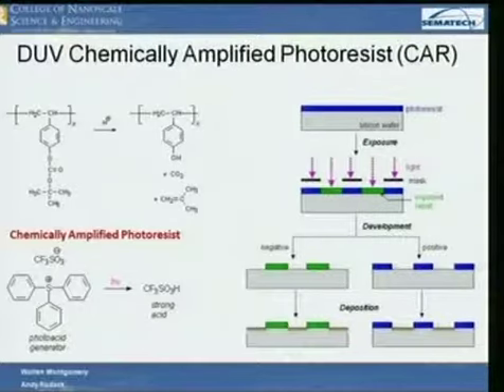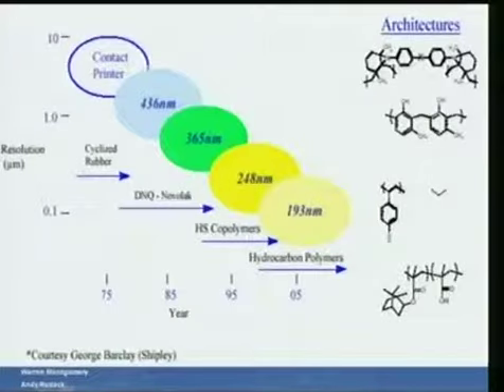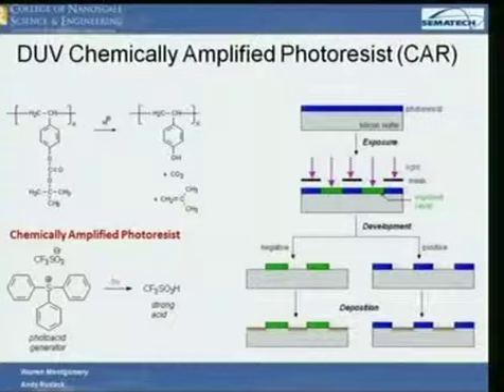And the other thing about that is that CO2 helps us, because if you expose something and you generate a gas, the gas comes off, what do you get? You get holes. So if you get holes in the area where you're exposed, what happens is the developer is able to penetrate the film better. So this thing had accelerated development because both of these gases would leave the film, and all of a sudden developer's coming in and had a place to go. It could go in where the gas left. So it develops like crazy, and that's very good. We like that. Fast development, fast throughput, get it out fast. These resists are very fast.